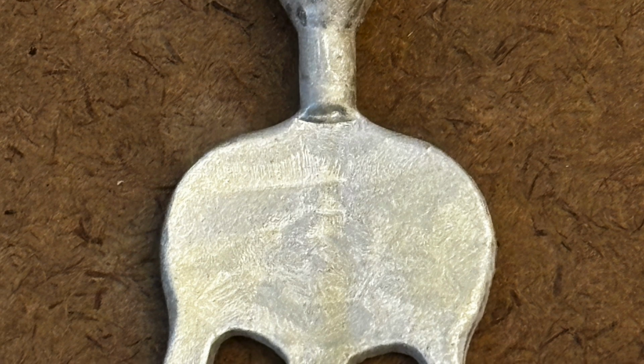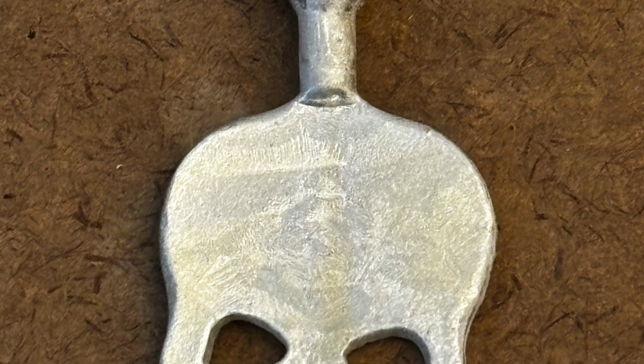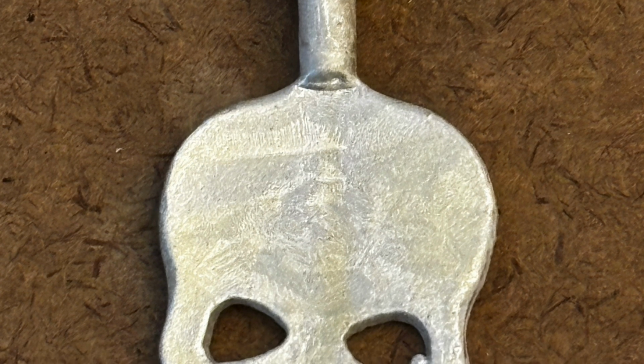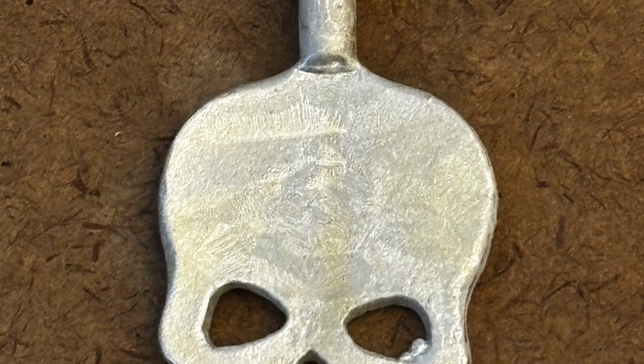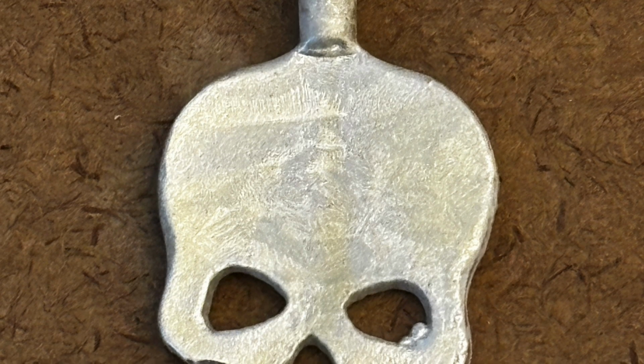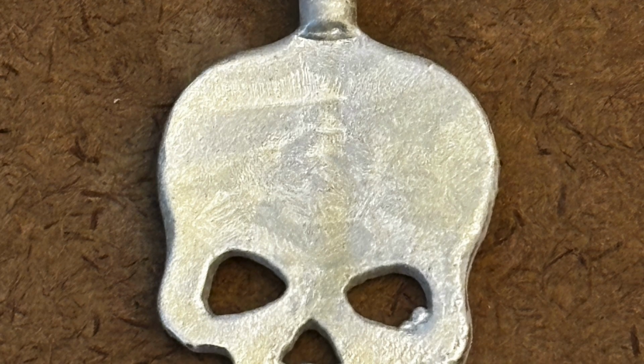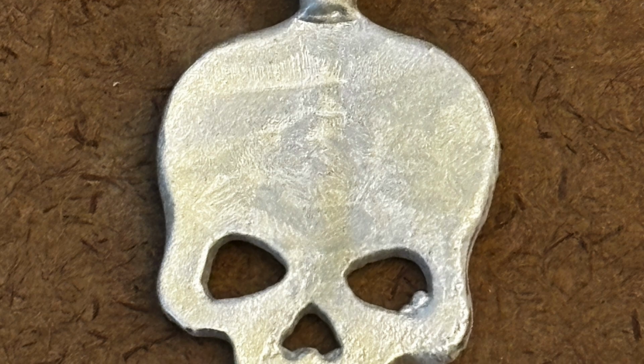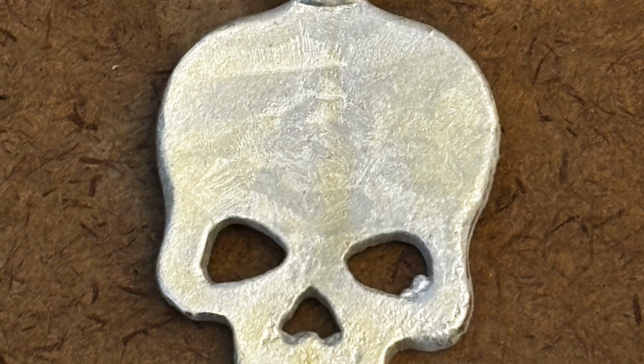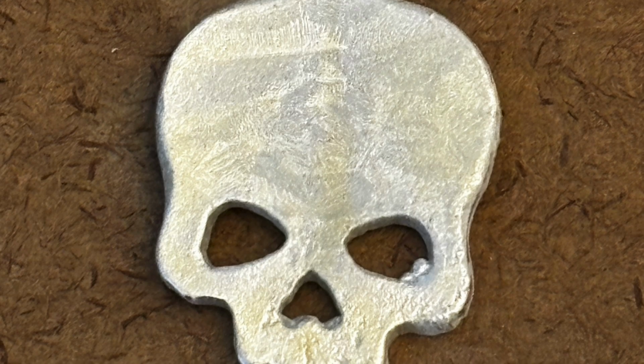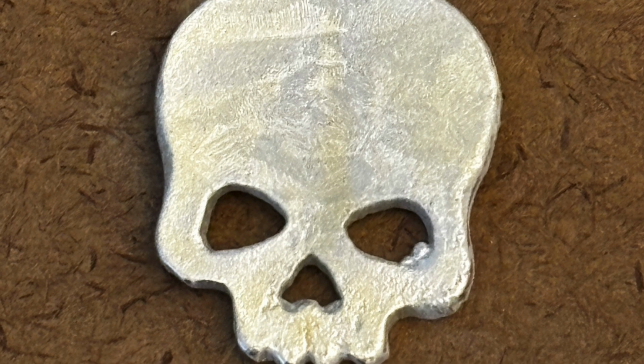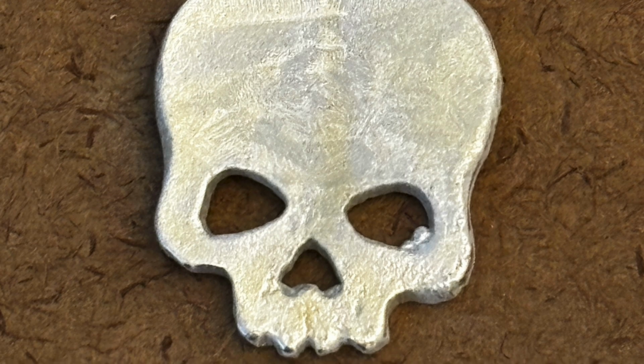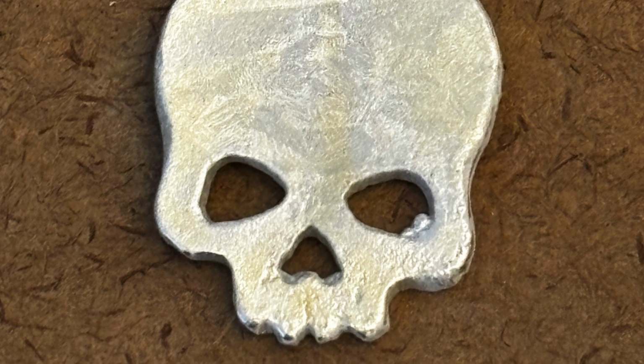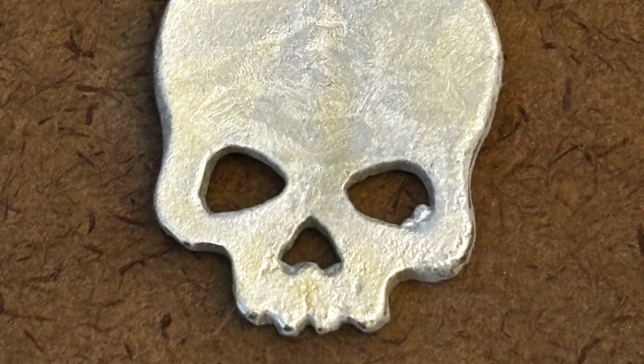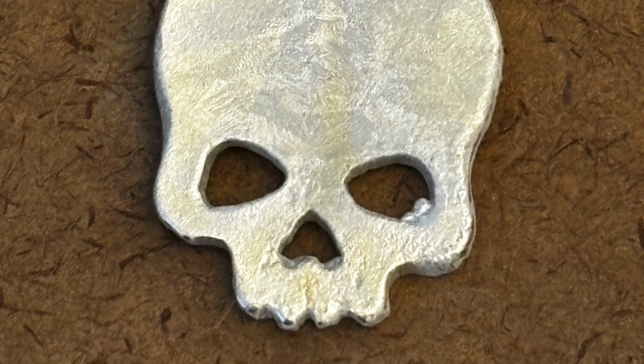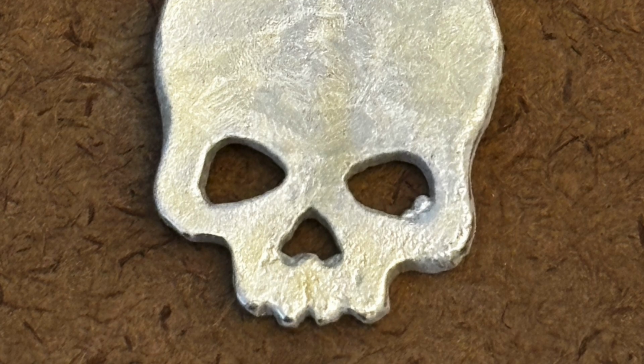Now again, it could be an effect that you like, and in this particular case, remember that your original with a successful pewter casting is going to have to be a bit thicker. And I tried that other Happy Witch, which worked great for wax injecting, but just really did not turn out well because of the thinness of the areas within the mold. So if you are thinking of pewter casting, definitely recommend having a much thicker original. In this case, it was probably a brass piece plate closer to about 1/8 of an inch thick. So you're still going to have some little areas to clean up, but much more successful with the pewter casting process that we'll now take a look at.